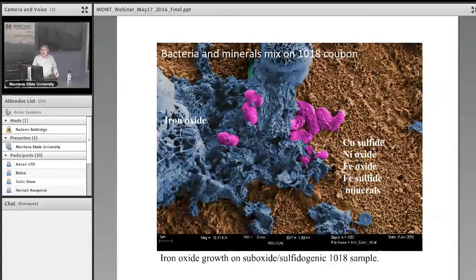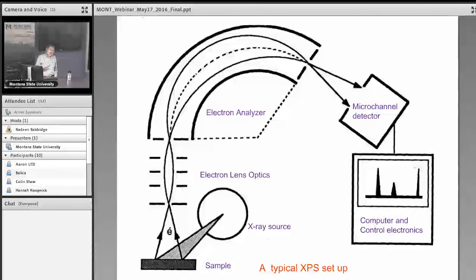And iron oxide, different morphologies. You can sometimes tell something with iron oxide simply from the morphology, but it takes experience. You have to do lots of these things. So copper sulfide, nickel oxide, and sometimes elemental copper, you see these things. So let's see how we can tell that it was, say, calcium carbonate, not something else, or that it was copper oxide, not elemental copper, the oxidation state. So that's where the XPS comes in.